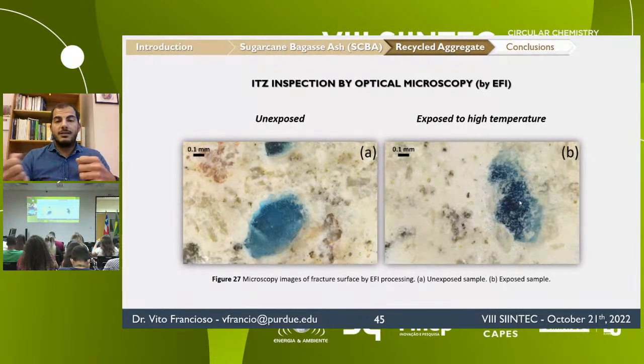But if we wait, when the sample is cooled down, the fibers can recover their strength because they solidify again, and in that way they have also penetrated the pores. So that's why the secondary strength was higher for the cooled samples than the standard samples. So in a certain way, this is a treatment of the fibers.